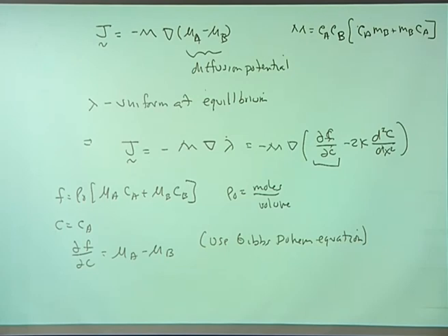And so that means that, okay, I'm sorry, I'm going a little bit faster. So if you take this equation here, take the derivative of F with respect to C_A, and you use the Gibbs-Duhem equation, you come up with this equation here. And you can see that this term here is exactly this. Exactly this. And so you basically have recovered the classic diffusion equation written in this volume-centered frame plus a correction term due to the gradient energy coefficient.